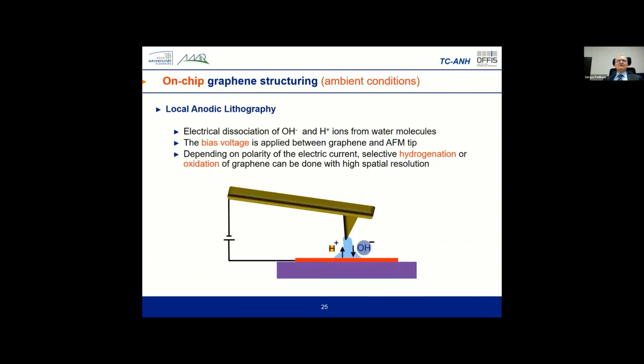Staying with graphene, we developed a new technology to process graphene flakes on top of a processed chip, which is pretty difficult, because you can do this only sequentially using, for example, the tip of the AFM cantilever. There is no other way, because you have the chip, you have the graphene flake here, and you have to process this flake to induce a new feature. So we use hydrogenation and oxidation of graphene here, using the well-known technology of local anodic lithography. It depends on the polarity of the voltage which you apply between the tip and the graphene flake.